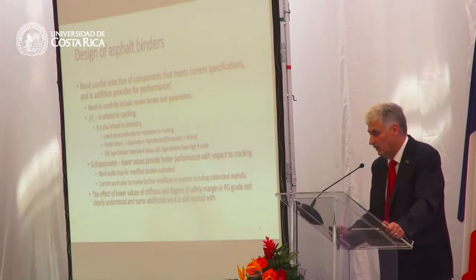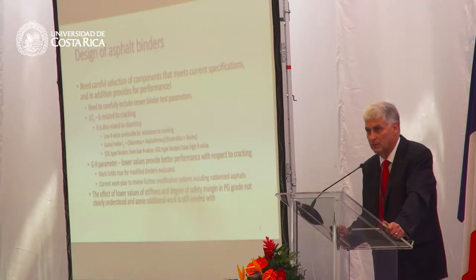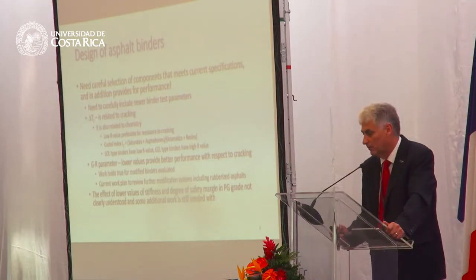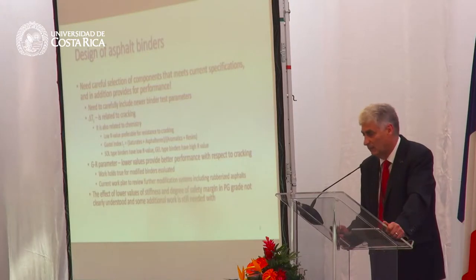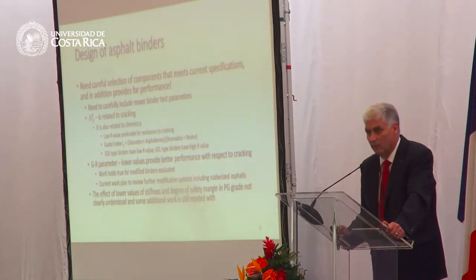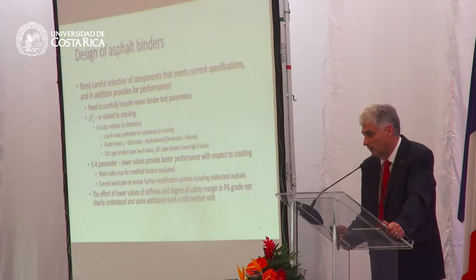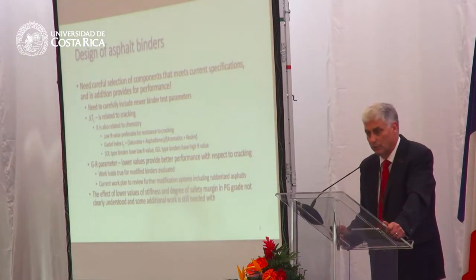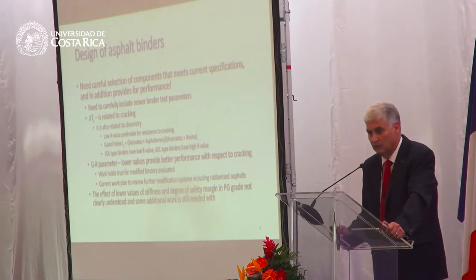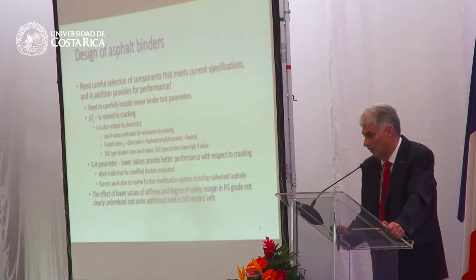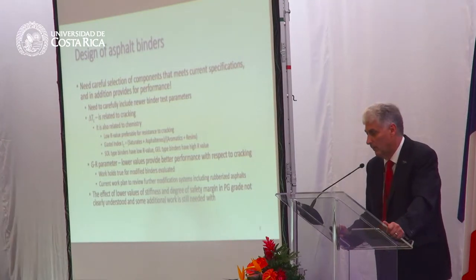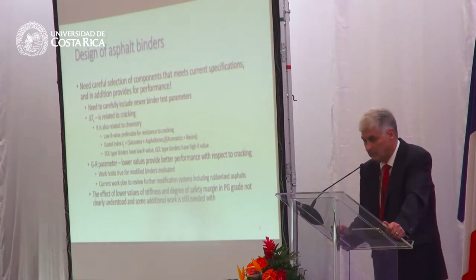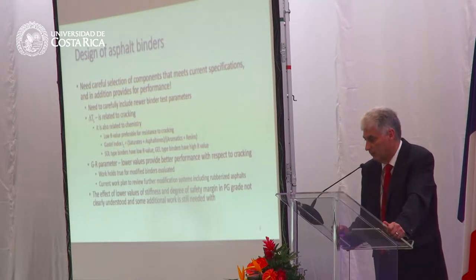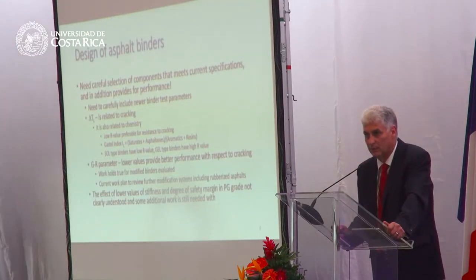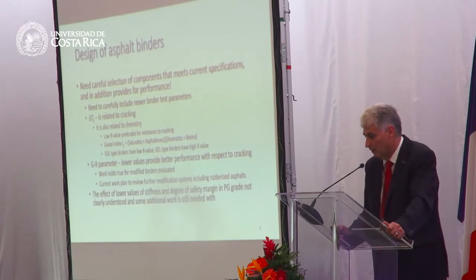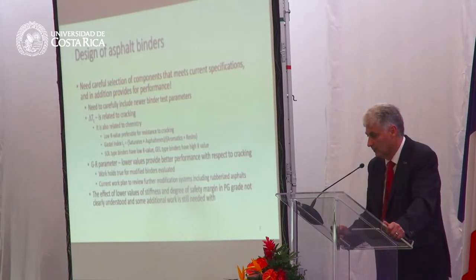The other parameter is a parameter called the Glover-Rowe parameter. This was work that was originally developed by Charles Glover, and now it has my name tacked on there as well. But we've been looking at that parameter as well as the delta TC for trying to understand both conventional and modified binders. And so far, we found that it works fairly well for all the binders that we've looked at, including rubberized asphalts. So what these two parameters do is they allow us to understand the effect of stiffness and relaxation properties with the binders, and I'll talk more about this in a few minutes.